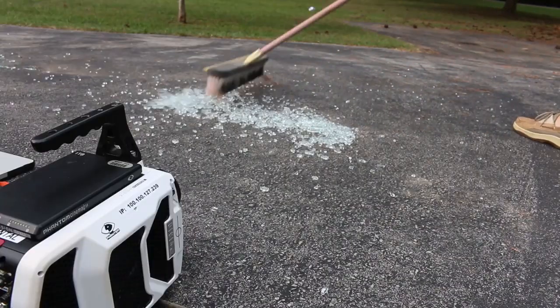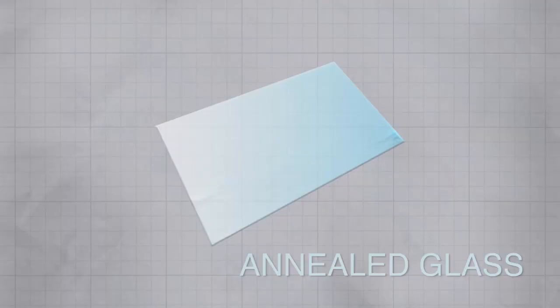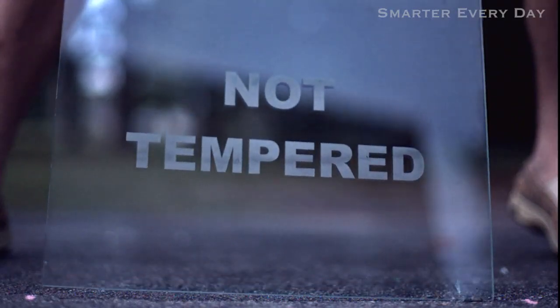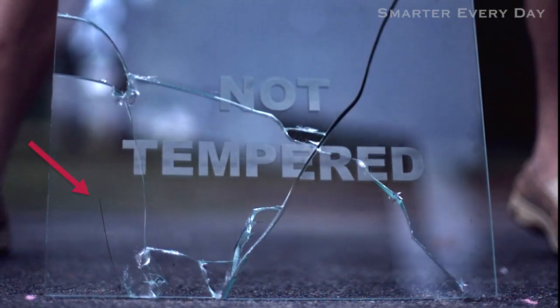Okay, so what did we learn from this experiment? Annealed glass is just normal glass that's been heated up in the manufacturing process and then allowed to cool down gradually. This cooling relieves any internal stresses on the glass. You'll notice when the annealed glass breaks, not only is the cracking slow, but sometimes it doesn't even make it to the other side of the glass, which is good for windshields.